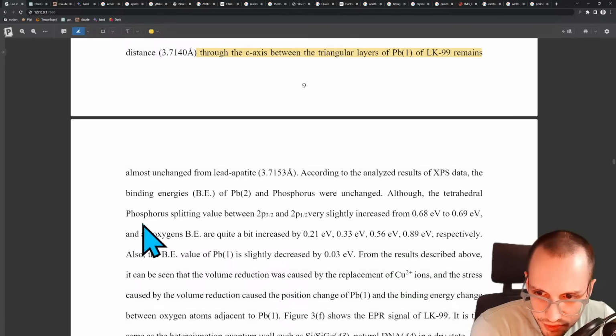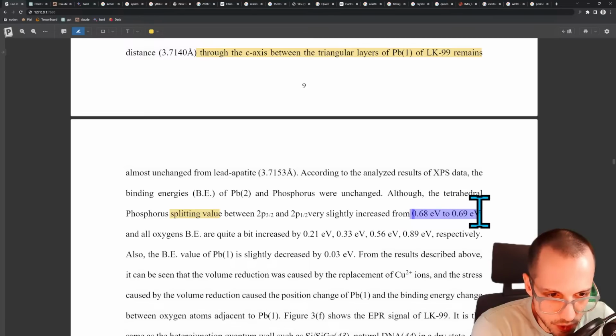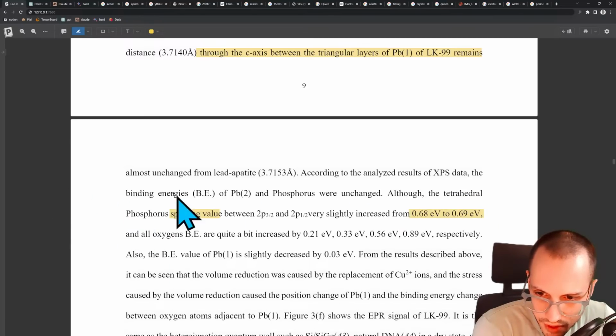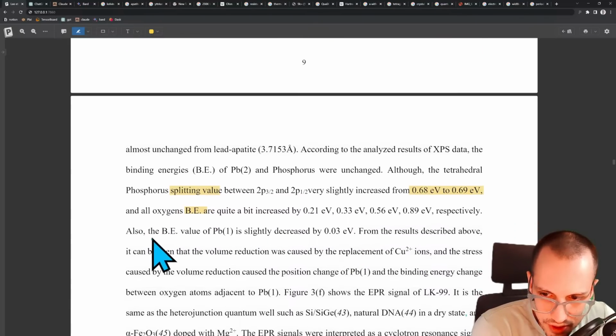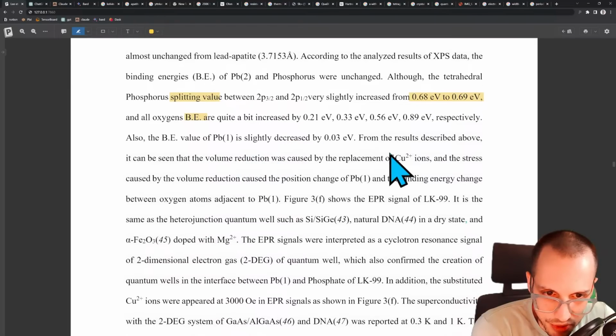Although the tetrahedral phosphorus splitting value very slightly increased, so I guess this is the amount of energy required to split this phosphorus out, and all oxygen's binding energies are quite a bit increased by 0.21, 33, 56, and 89. And then the binding energy value of Pb1 is slightly decreased. From the results described above, it can be seen that the volume reduction was caused by the replacement of the Cu2 ions, and the stress caused by the volume reduction caused the position changes of the Pb1 and the binding energy change between oxygen atoms adjacent to Pb1.